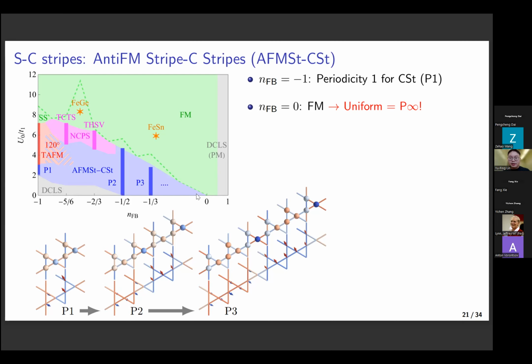So indeed, if we look at a state in between, we are seeing a cascade of spin and charge stripe order with increasing periodicity. For example, if we look at the negative half filling of the flatband, which is half filling between -1 and 0, we're seeing that the charge periodicity is becoming twice, and correspondingly, the antiferromagnetic stripe is also increasing in periodicity.